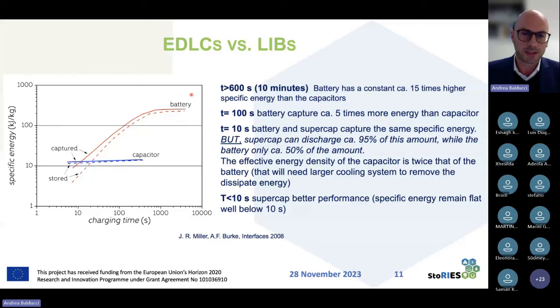What we can see is that if you are considering a lithium-ion battery and a time frame larger than 10 minutes, there is actually no comparison, because the battery displays much higher energy than the supercapacitor. So it doesn't make any sense to use a supercapacitor if you want to go in the range of 10 minutes.